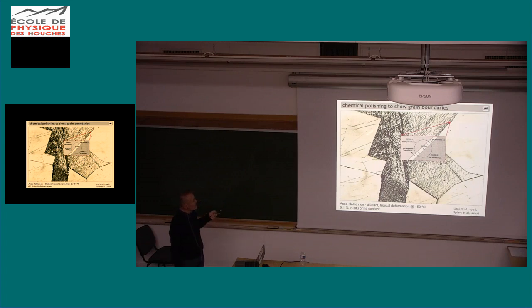And that technique suddenly opened up the microstructure of salt, and what we have seen is that all the samples that we have studied that did not dilate were recrystallized. There was a subgrain structure with a subgrain size exactly as expected, and there were lots and lots of big new grains without any dislocations.